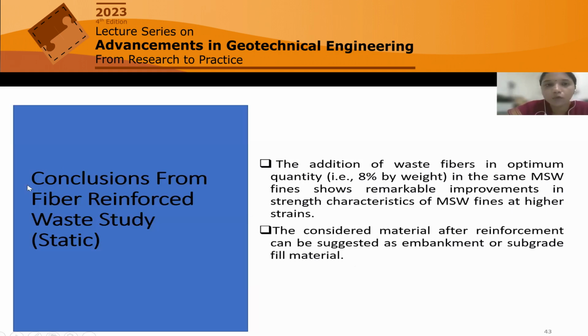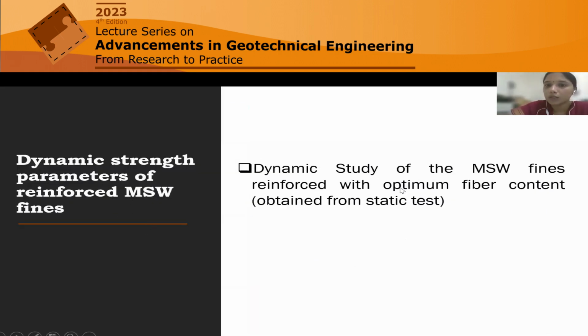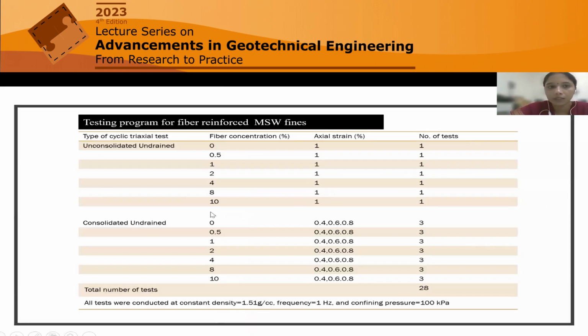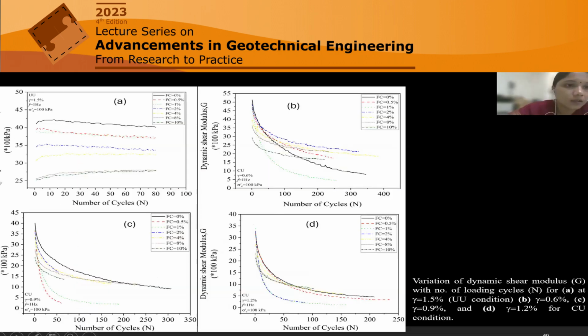Then for this fiber reinforced part, we also tried to explore the dynamic strength parameters. Here we considered the optimum fiber, but performed limited tests. We performed unconsolidated undrained (UU) and consolidated undrained (CU) tests. For the UU test, we considered one axial strain for different fiber content. For the CU test, we varied the fiber content from 0.5 to 10%, but tested only three axial strains. We kept the density constant at that of MSW fines, 1.51, with frequency 1 Hz and confining pressure 100 kPa. From this, if you see the dynamic shear modulus versus number of cycles curve, there is not much change in the dynamic shear modulus value for different fiber contents in the UU test, particularly unconsolidated undrained.